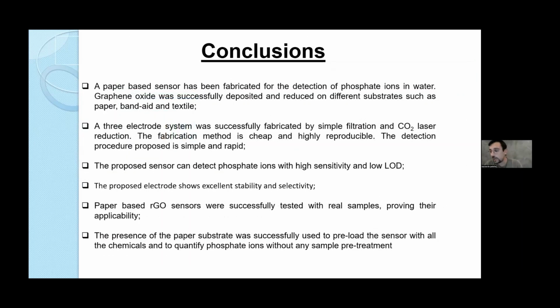So concluding, a paper-based sensor has been fabricated for the detection of phosphate ions in water. Graphene oxide was successfully deposited and reduced on different substrates such as paper, band-aid, or textile. A three-electrode system was successfully fabricated by simple filtration and carbon dioxide laser reduction. The fabrication method is cheap and highly reproducible, and the detection procedure is simple and rapid.